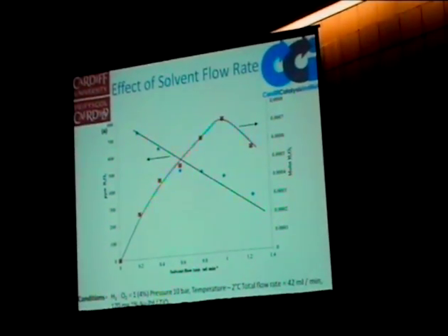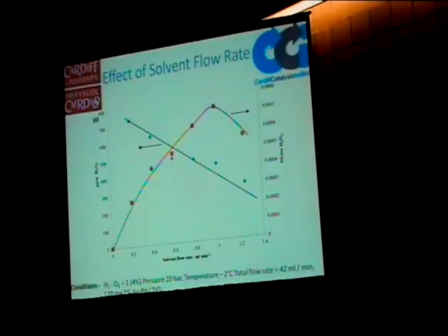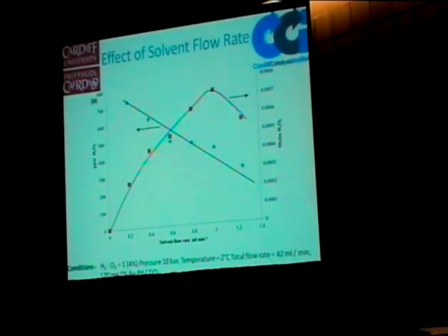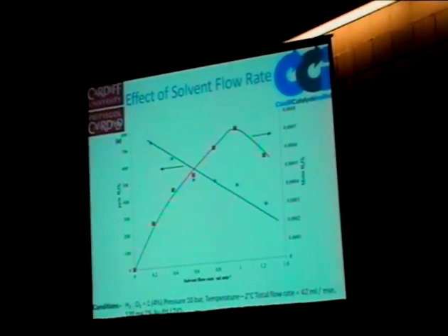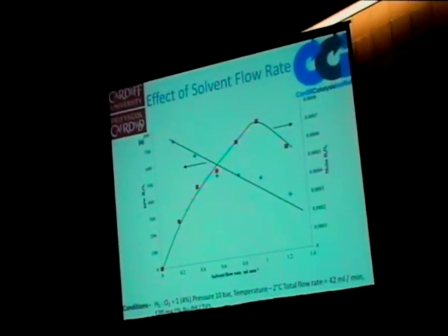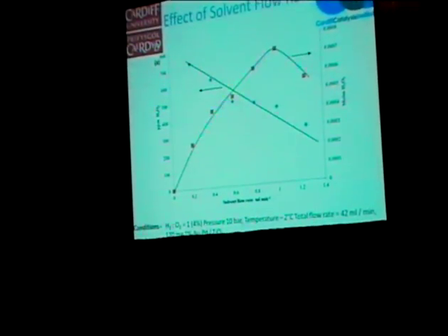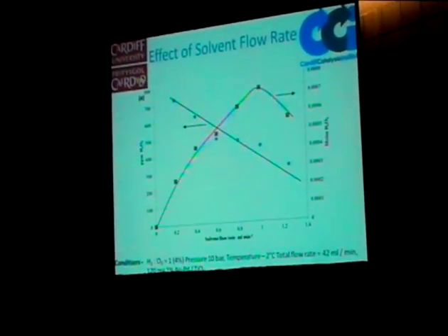So we looked at the effect of the solvent flow rate. As we put more solvent through per minute, we saw an increase in the concentration of hydrogen peroxide that we were making. Although if we calculated the number of moles we were making in 1 hour, we actually saw a decrease in the number of moles with the solvent rate. So we thought this was quite interesting.